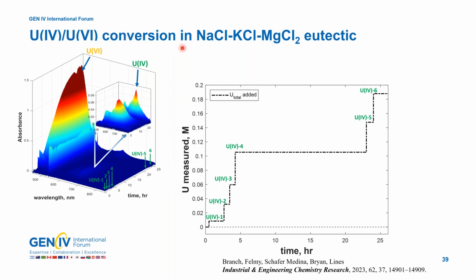And this slide shows one of the experiments that we performed to look at the uranium-4 to uranium-6 conversion, where we start with using a chloride eutectic salt. This shows the concentration of uranium that we measure from our chemometric model as a function of time. And just to start out, we start with a clean eutectic with no metal involved. We add a uranium-4 salt in different increments in the first several hours and let it sit overnight. And then we add some more uranium-4 at the end of the experiment. And shown over on the left-hand side are the UV vis spectra as a result of those salt additions.